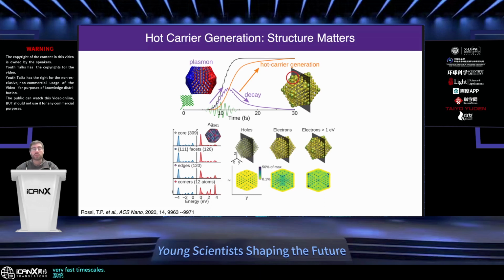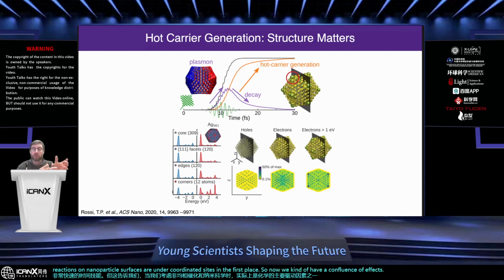But what this tells us is that when we think about heterogeneous catalysis and we think about nanoscience, really one of the main drivers of chemical reactions on nanoparticle surfaces are under-coordinated sites in the first place. So now we have a confluence of effects. We have under-coordination of small nanoparticles, which is known to bind molecules very strongly and change energetics of particular chemical pathways. But we also have, under illumination, this generation of electronic carriers that have energies that are greater than 1 eV. That means that if a molecule sticks to the surface, and has a reduced activation barrier because of that binding event, we can now utilize those hot carriers or those electrons to drive chemical processes with a little bit more ease.